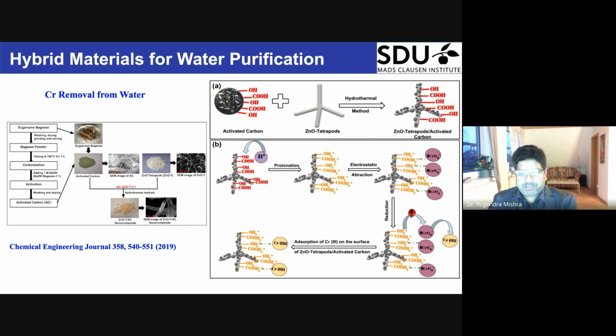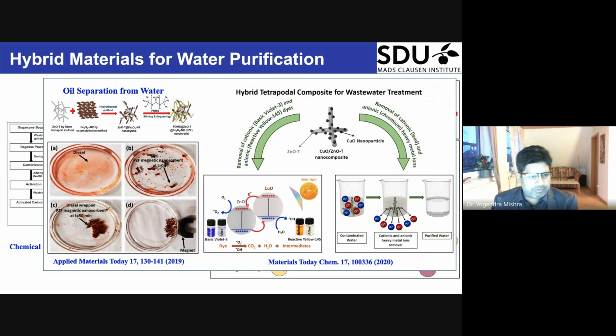In fact, we have demonstrated, by Dr. Monica Joshi from Amity University, she was coating these tetrapods with activated carbon, and this showed a nice decomposition of chromium 6 into chromium 3. She was also coating them with magnetic nanorods, iron oxide, encapsulating, and very nicely the separation of diesel from water was demonstrated.